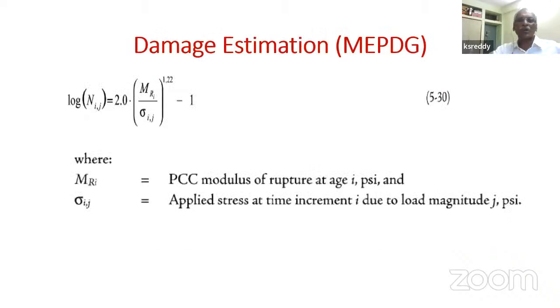This is what we do in IRC also for estimating what is going to be the fatigue life, so that we can estimate the damage index as a function of what is the stress produced by a given load, what is the flexural strength, which is called the stress ratio. This is what we do in IRC 58 also.